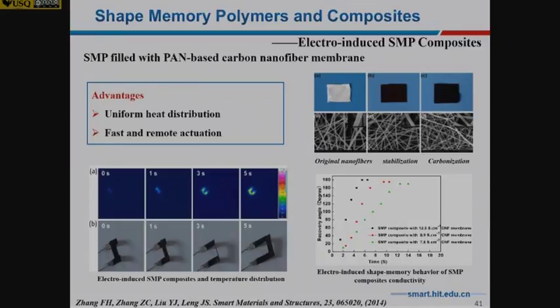Another one is we tried using PAN. PAN is another conductive nanofiber membrane. With this one, we can also do the shape recovery during the heating. It's very fast, only 5 seconds. This one can deploy.